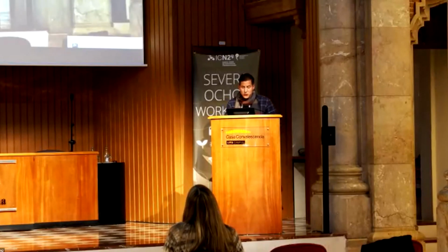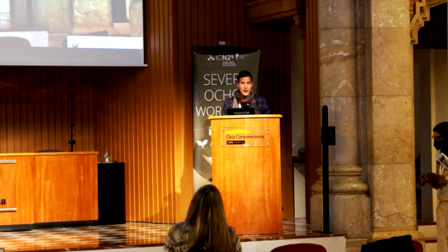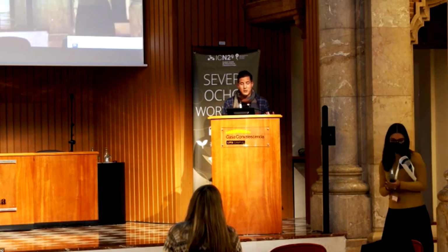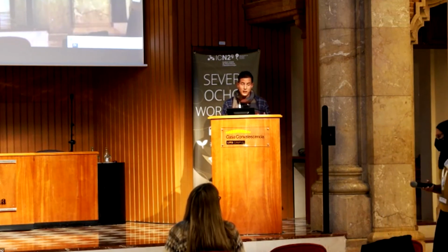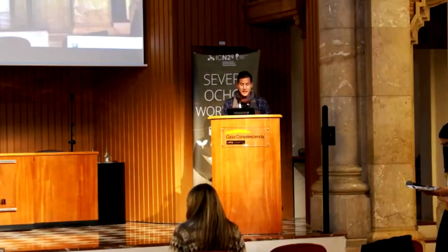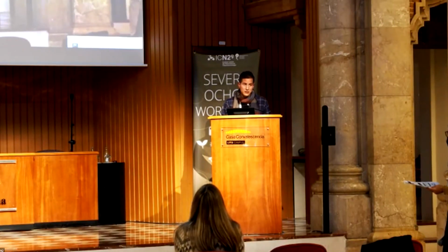When I grew the polymer shell on the silica, I functionalized the surface of the silica with a silane cross-linker, called methacrylate silane, which converts the surface into vinyl groups. Basically this particle becomes hydrophobic immediately, so they need to be dispersed in hydrophobic solvents. So no need to check the pH. The pH did not dissolve the particles.